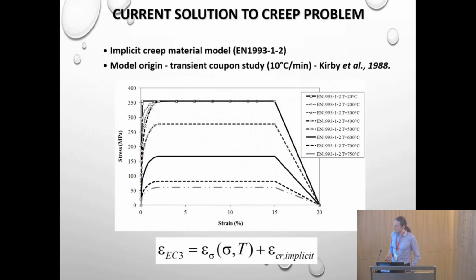So the current solution to the key problem as it exists in structural codes is the implicit creep material model, which is present in Eurocode 3, which is based on this type of testing. And its origin relates to a transient coupon study, which was done in the 80s by applying a heating rate of 10 degrees per minute. And as a result of this coupon study, we have a stress strain law, which is very familiar to you. And with this stress strain law, we have an implicit creep component, which is contained in its mechanical strain. So this was the starting point for the research project.